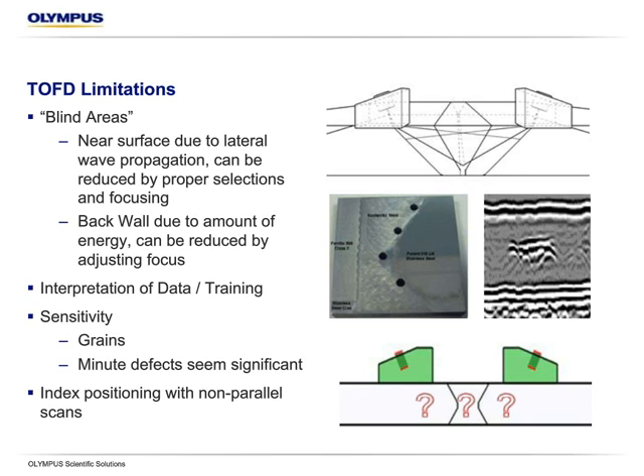Typically when you use one pair of TOFD, we're only thinking about focusing at usually 2/3 and then flooding the entire component with sound and trying to get a 2-probe full coverage type setup. We could actually do a second scan, separate those probes out further and focus it, say, 90% or somewhere near that, near the back wall. Or we could use a scanner that could hold 2 sets of probes, and we can prove up on a reference reflector that basically that dead zone or blind area is pretty much reduced to 0.